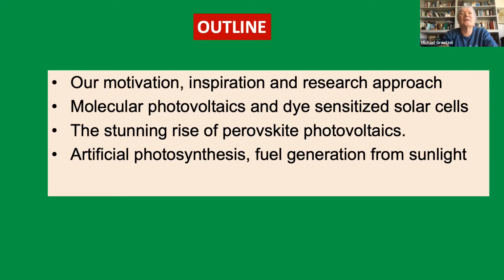And so out of this inspiration and our research approach, which was to go to the nano dimension and the molecular sensitization, came out the molecular photovoltaic field and quantum dot sensitized and dye-sensitized solar cells. And then this led, as I said, to this rise of perovskite. And finally, today we can make fuels from sunlight. For example, we can split water using just a perovskite silicon tandem with 18% efficiency into hydrogen and oxygen. And we can also turn CO2 into ethylene.